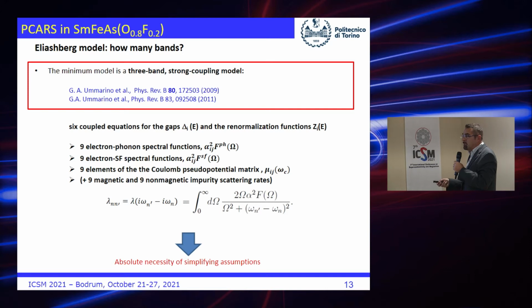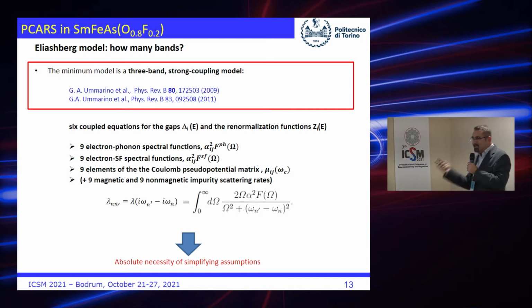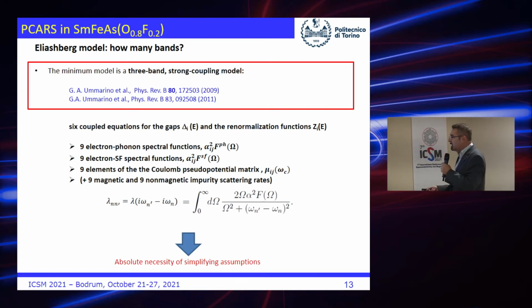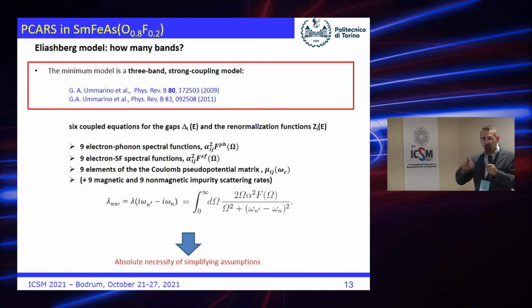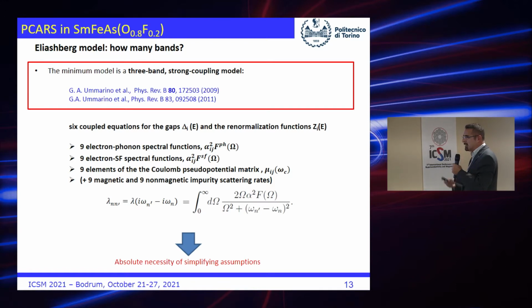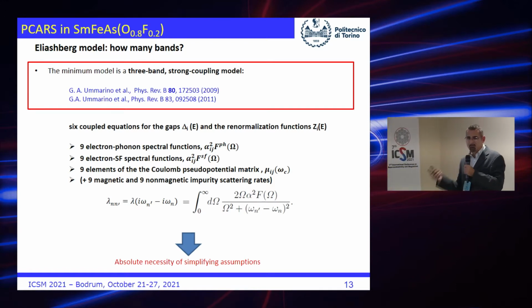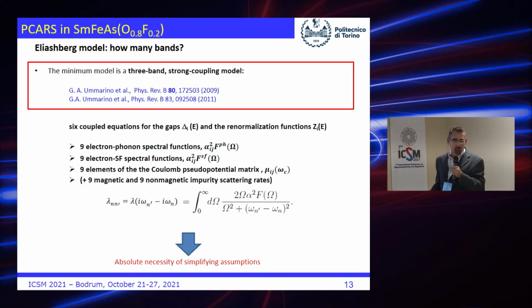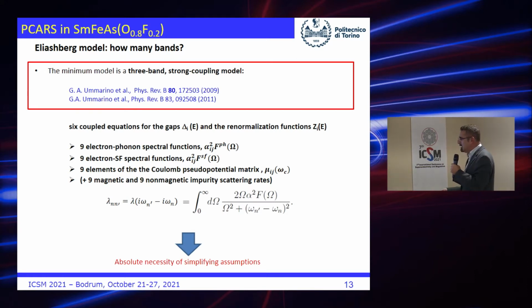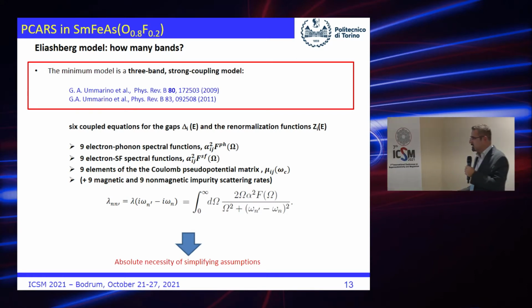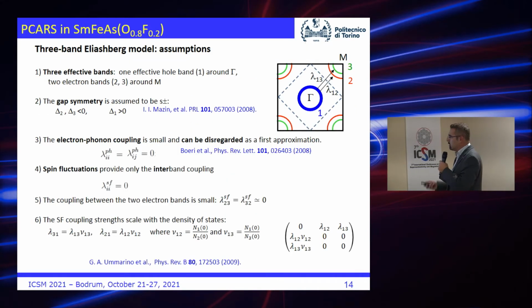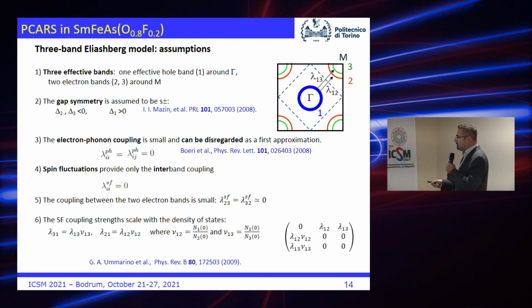9 electron-spin fluctuation spectral functions. 9 elements of the Coulomb pseudopotential matrix, and if we want to be very precise, we also want to include scattering. We have 9 elements of the scattering rate matrix and 9 elements of the magnetic one. Well, it's impossible, of course. We absolutely need some simplifying assumptions. Well, the assumptions are the following. First, we have 3 bands. For this compound, we chose one effective hole-like band around gamma and 2 electron bands around M.